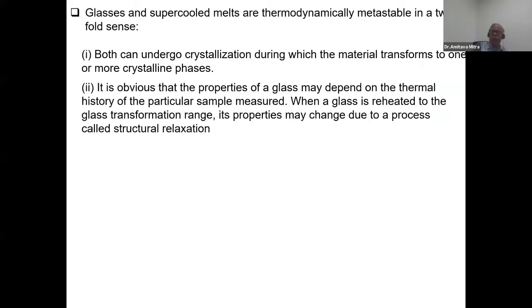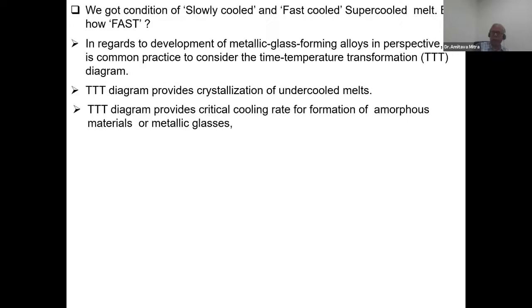For which we have to go for some time temperature transformations. So glass and supercooled melts are thermodynamically metastable, as already told. Both can undergo crystallization during the material transformation into one or more crystalline phases. It is obvious this property of glass may depend on the thermal history of the particular sample, and that you also discussed as structural relaxation.